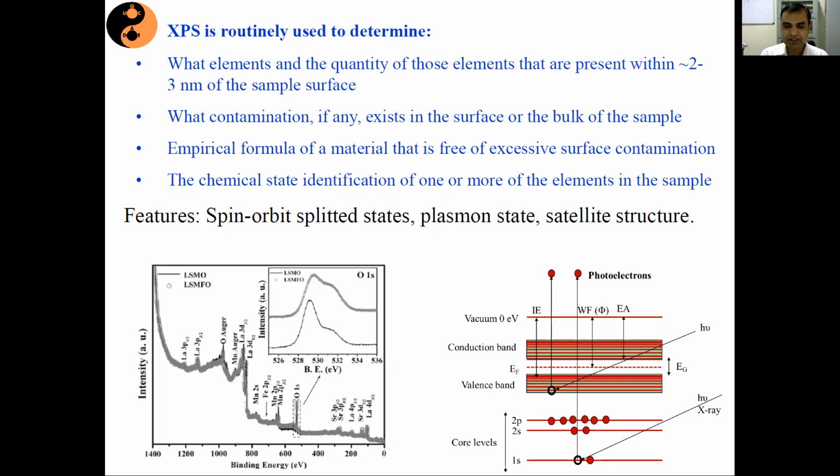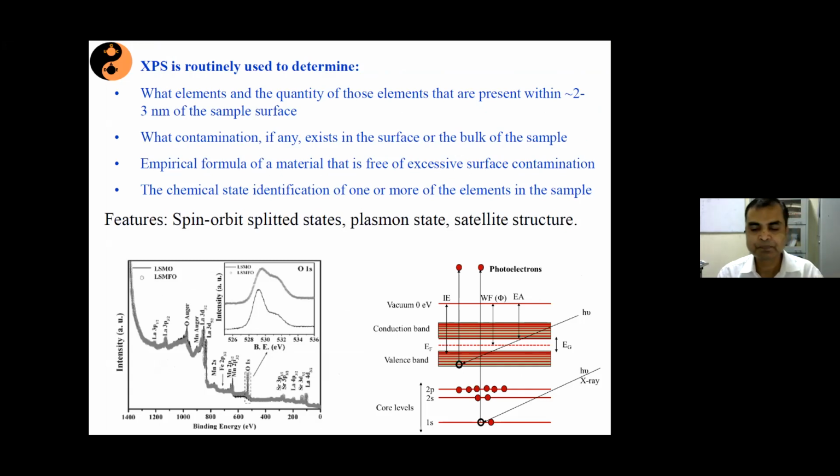photoelectron is coming out, the whole purpose is to measure its original binding energy. And to measure its original binding energy, we really need to know its original kinetic energy, because we have hν equals binding energy plus kinetic energy plus φ. Okay, so our experimental setup is configured in such a way that the work function of the sample does not come into the equation; rather it's the work function of the spectrometer. So that is always constant for any material, or for different experiments.